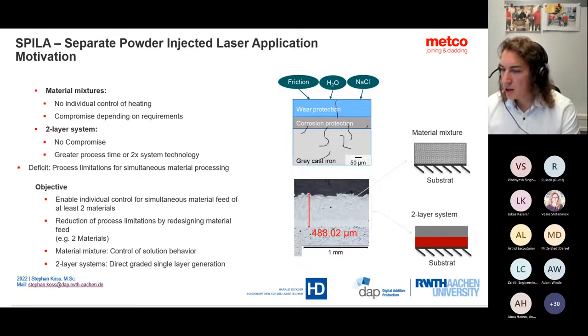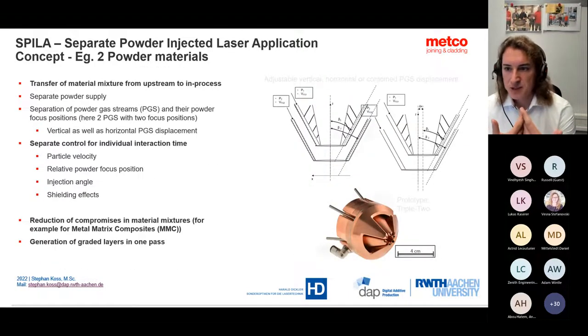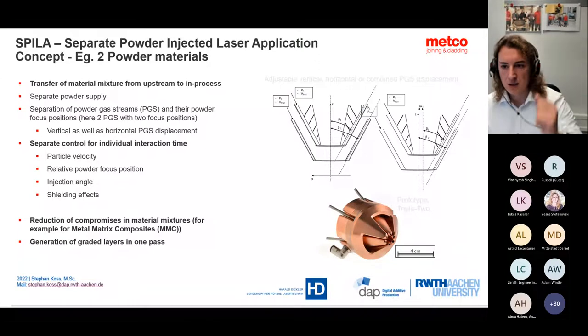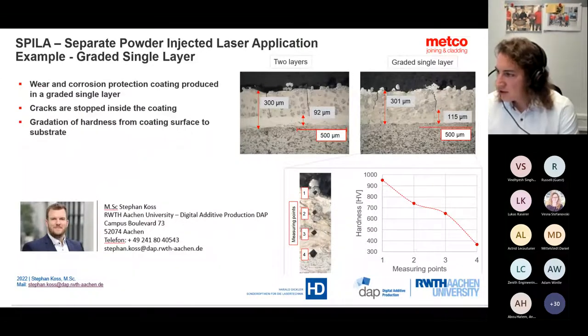So one of the motivations was, is there any chance, working with special nozzle developments, to produce so-called gradient structures where, for example, you can work with different interaction angles of powder particles with the laser beam, and as a result produce graded layers in one layer deposition, having a softer layer on the bottom and then carbides on top. It was quite interesting to find out that the first results going in that direction help you to produce metal matrix composites. You can very well recognize that you still have those carbides compared to the two-layer system, but this is produced in one layer, and also the crack propagation at a certain stage stops, which then acts as a buffer layer, and you get a high quality coating with one layer deposition and also not having any environmental troubles in terms of corrosion.